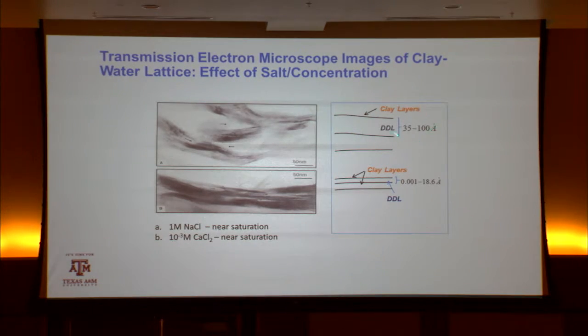This gives you some illustration of the actual thickness in angstroms, which is just a unit of measure, 10 to the minus 10 meters. You can see the distance between the individual layers, which is much greater in the sodium-saturated system than in the calcium-saturated system. So when I add cement or lime, which is a calcium-based stabilizer, to a clay soil, I'm saturating that clay with calcium. The calcium is suppressing the double water layers. It's making these tectoids, which are agglomerations of the individual plates to form particles, stiffer and stronger. So immediately the clay has gained stiffness. It's become a higher modulus. It's gained strength. It has a higher shear strength, and it's volumetrically more stable because of the addition of the calcium-based stabilizer.